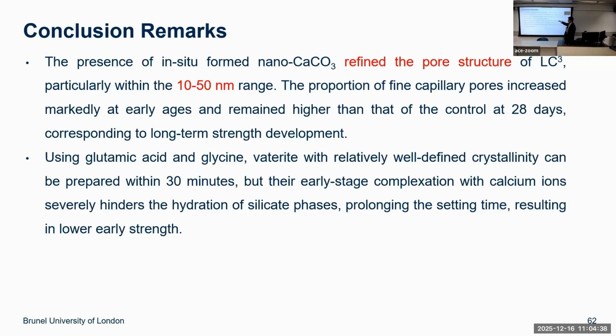It reduces the pore size, with many pores between 10 to 50 nanometers. They are less detrimental to the strength. And the proportion of fine capillary pores increases as well. So this markedly improves the early age strength, up to 28 days, and also long-term strength development.